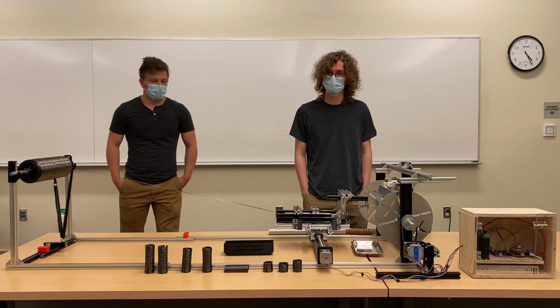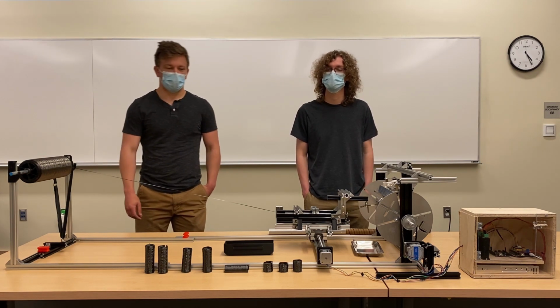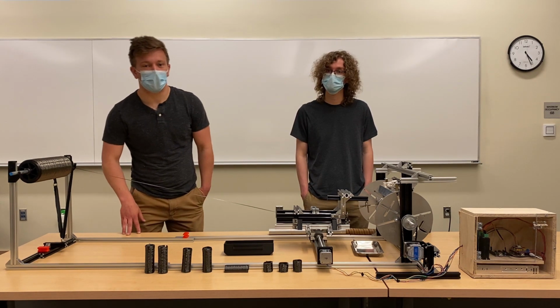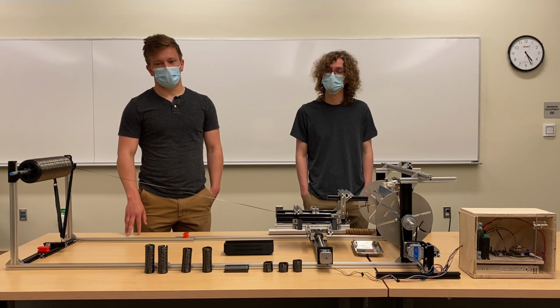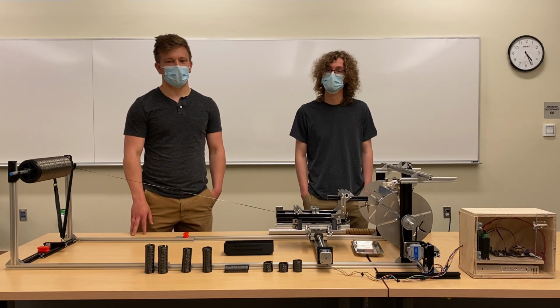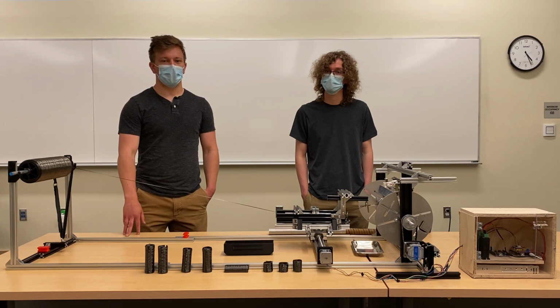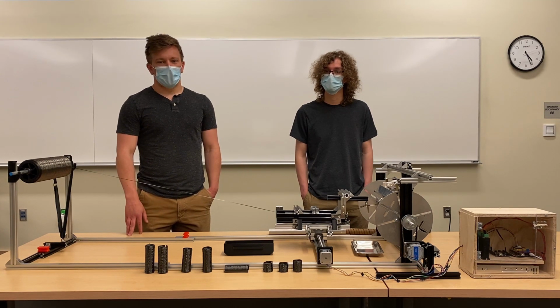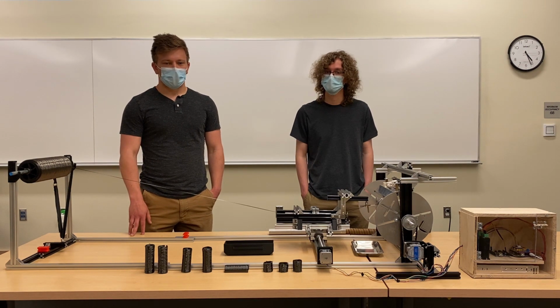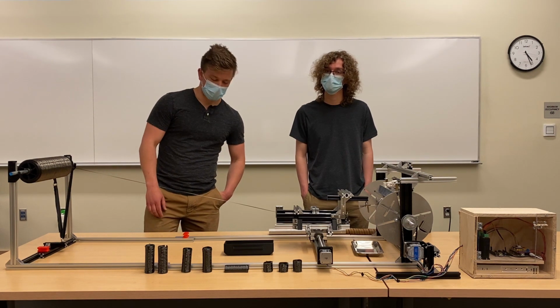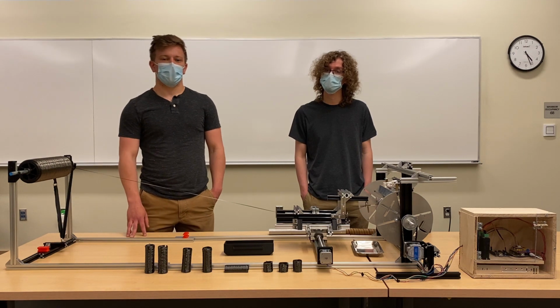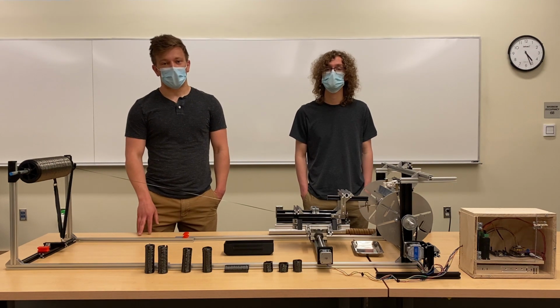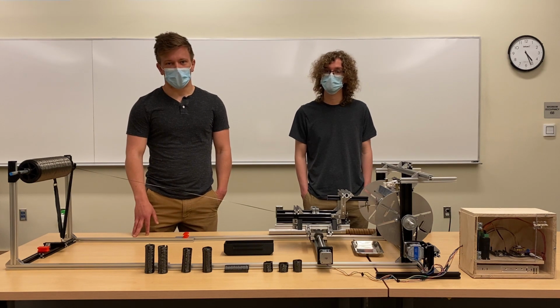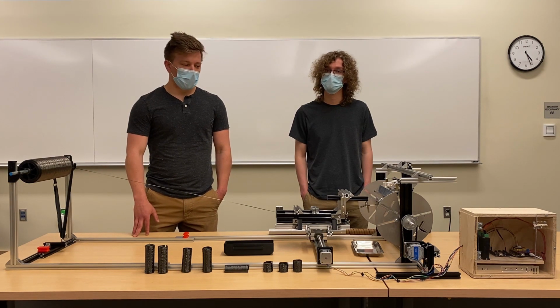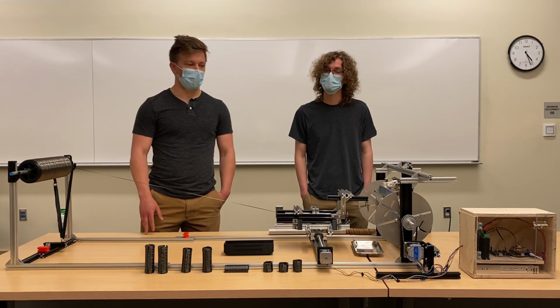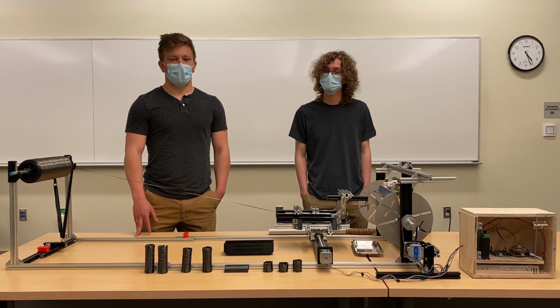Once this winding process is completed, the mandrel is removed from the winding mechanism and is placed into an autoclave where the sample is exposed to high temperatures and pressure. This is a very energy inefficient and time-consuming process, which takes multiple hours or even days for the resin to fully cure. A great example of this is here at CSU, where we manufacture a small 4" by 4" composite panel that has a curing cycle of 5 hours. This is pretty standard for objects in industry. But ultimately, for our project, we seek to remove the secondary heating process from filament winding.